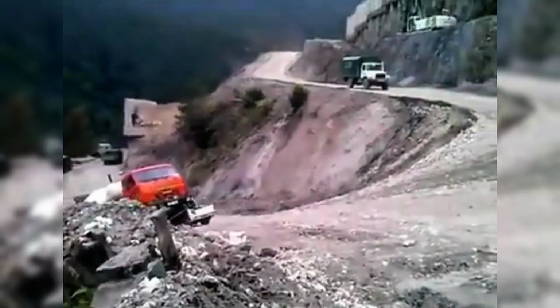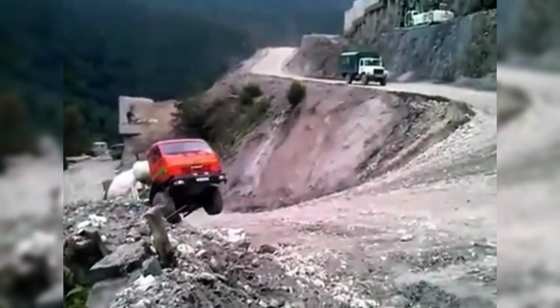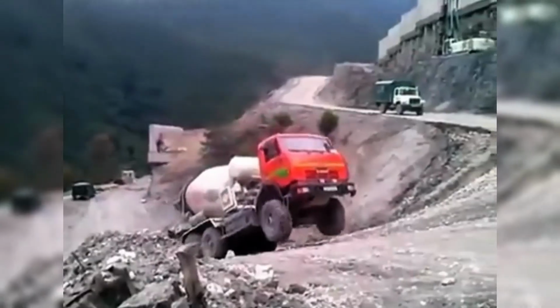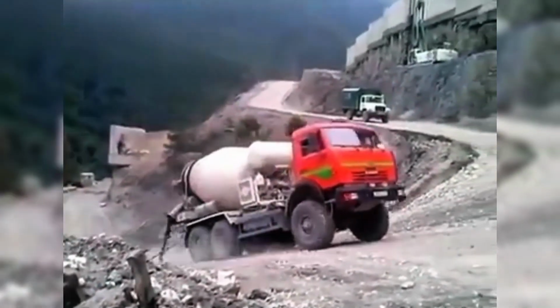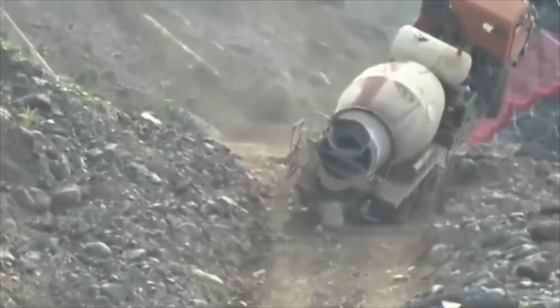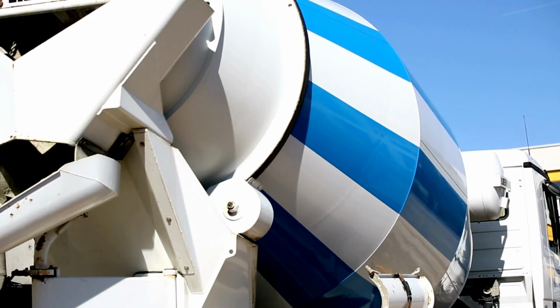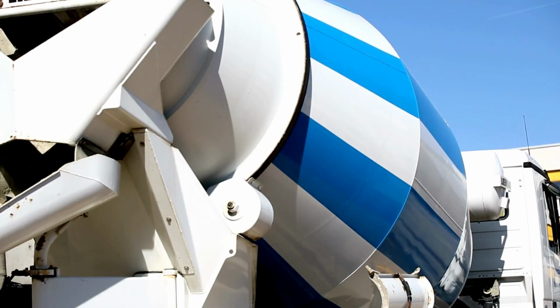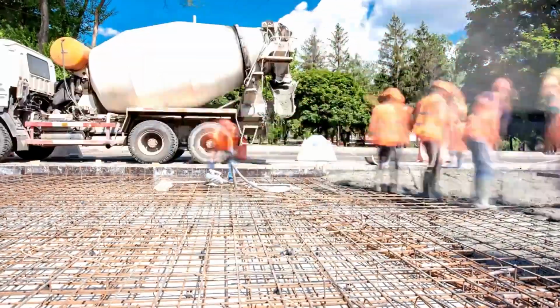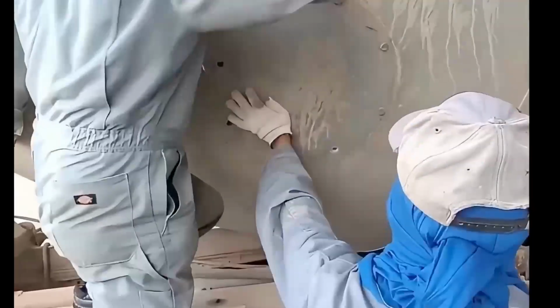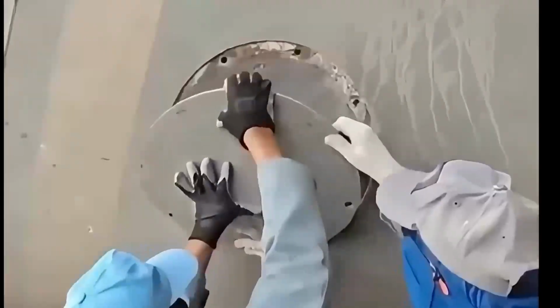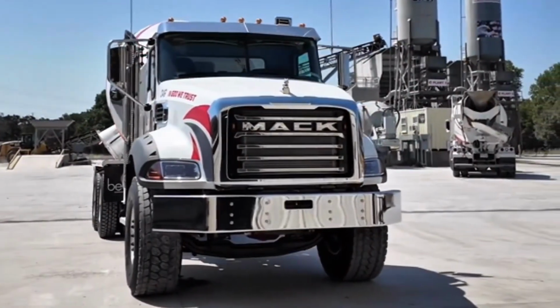Here is something most people never think about. When a fully loaded mixer climbs a steep grade, it looks like the concrete is about to pour straight out the back. It does not, and the reason is counterintuitive. It is not centrifugal force that keeps the mix inside. It is the geometry of those internal blades. When the driver increases drum RPM on an incline, the blades actively scoop the concrete and push it deeper into the drum, toward the closed end.